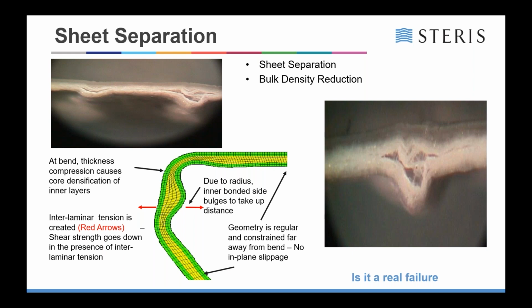And what that's doing is splitting the material at a certain point across the seal. So if that splits in the middle of, say, the Tyvek or paper, that'll be fine for today because you still have a sterile barrier. It may be fine, it may be accepted by your company, it may not. That is totally up to you. But if it does split at the clear film side, then you definitely will have a problem because you have a 99% chance of having a breach in your sterile barrier.